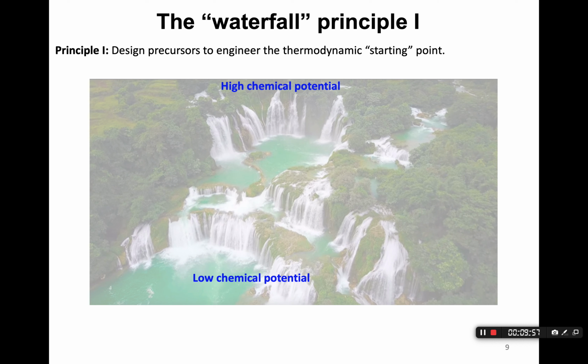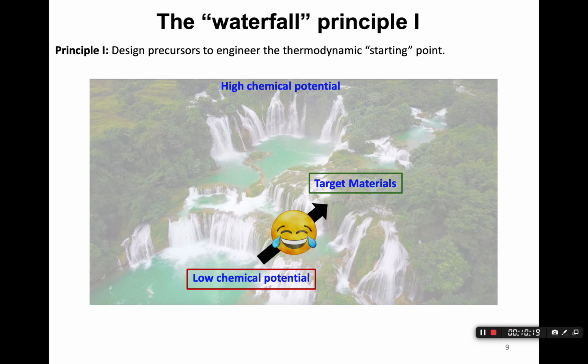And in most of the cases, the new materials that you want to make are something in the middle. They're metastable, but they should be reasonably metastable. If the energy is too high, you can never make them. So in that case, the reaction pathway becomes very important, because if you come from a low chemical potential, it is very likely you cannot make it, right? Because the thermodynamics does not drive this process. But if you start with a high enough chemical potential, it is likely that the reaction is going to happen and stay at some intermediate state. And you can use some experimental treatment to stabilize that metastable state. For instance, the usual thing we argue about this metastable phase is kinetic stabilization, right? So that is actually the basic idea behind designing the precursors.